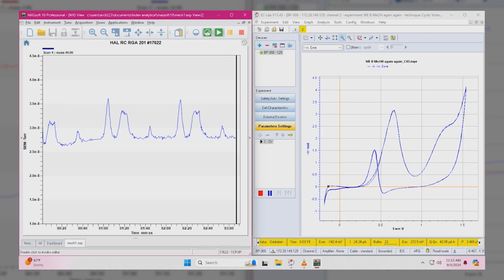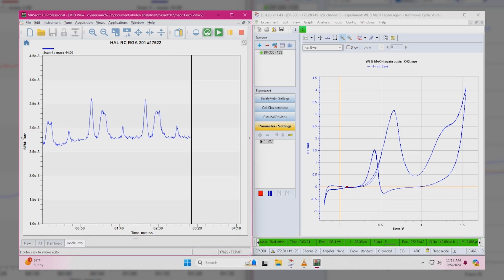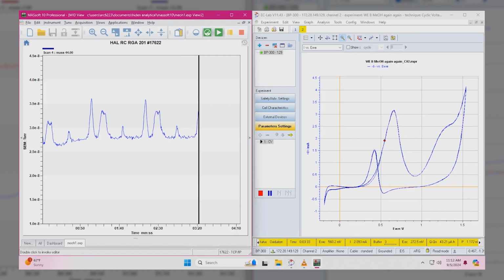So you can see as we start the scan and we start to scan forward in the anodic region, we see that we have this anomaly known as the low potential methanol oxidation wave, and you can see the production of carbon dioxide in the mass spectrometer almost simultaneously. And then we get to a more anodic region known as the high potential methanol oxidation wave, where carbon dioxide is being formed again, and then we see the onset of OER.